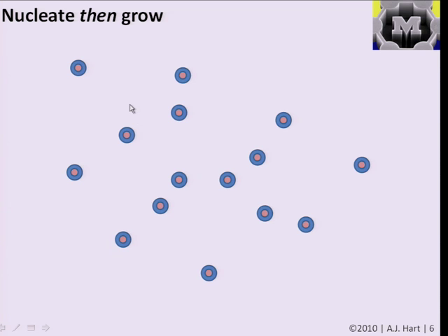And it actually agrees very beautifully with the observation we saw about how, for example, injecting more precursor into the solution to increase the supersaturation can change the growth dynamics. And what's happening is you are affecting how much source each particle sees, and that affects the relative consumption of source by particles of different sizes, and therefore puts the population in a regime where the growth rate depends on the size of the particle or does not depend on the size of the particle.